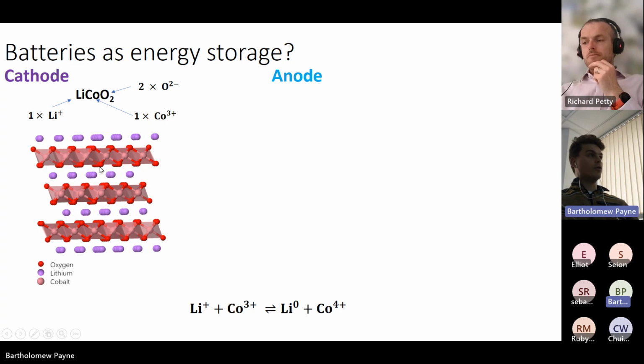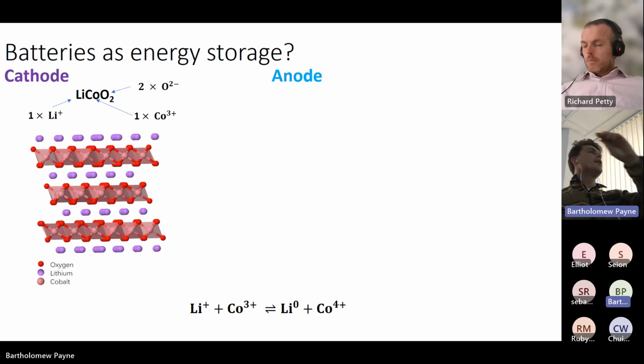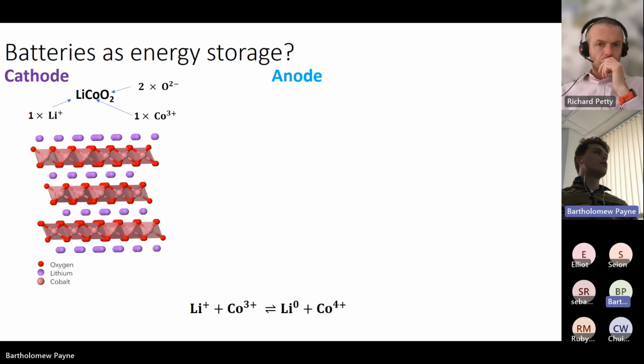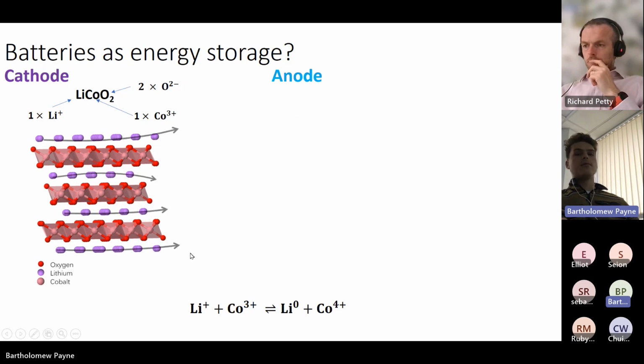And this is actually in the rock salt structure, the same structure as you see in table salt. It's just that instead of the chloride anions you've got oxide anions, and then you have layers of lithium 1+ and layers of cobalt 3+. This is the material which John Goodenough discovered in the 1980s and why he got his Nobel Prize. The great thing you can do with this material is take the lithium out. As you take the lithium out, the cobalt is redox active, and it can go from 3+ to 4+.